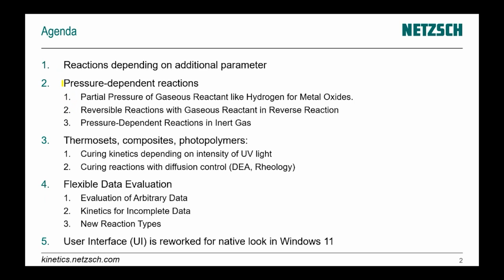For example, it could be pressure. For pressure-dependent reactions, we can now add pressure as an additional parameter. And here we have 3 examples. The partial pressure of a gaseous reactant, for example, hydrogen for metal oxides. Here the hydrogen is the reactive gas, and the higher the concentration of hydrogen, the higher the reaction rate, and we can create a kinetic model which takes this concentration into account.